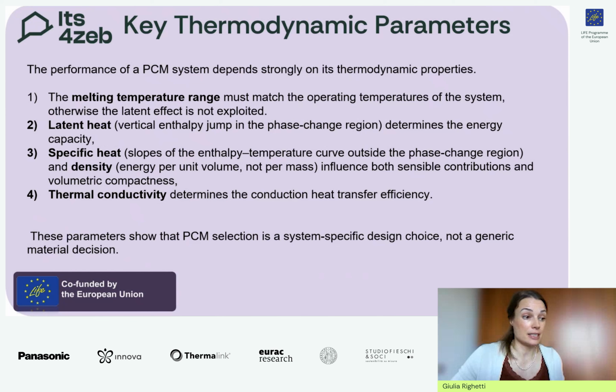Then we have the latent heat that determines the energy capacity. So the larger this parameter, the larger the latent heat, the higher the enthalpy jump and the bigger the storage capacity. Then we have the specific heat and the density. They both influence the sensible contributions and the volumetric energy density. The volumetric energy density is the energy per unit volume. So it's what matters in real systems, because it's how much energy I can store in a defined volume.